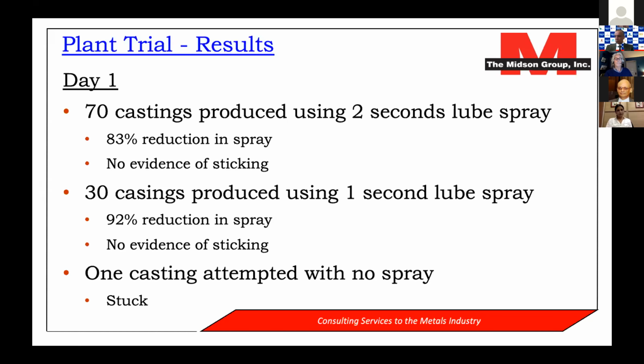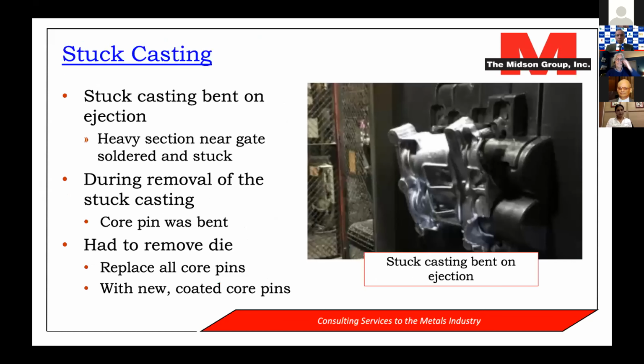And not only did it stick, but it actually bent on ejection, as you can see here from the photograph. And so it looks like heavy sections close to the gate soldered and stuck. And then during removal of the stuck castings, some core pins were bent, so the die had to be taken off the machine and disassembled. Luckily, we had spare coated core pins that we could put back in, reassemble the die, put it back on the machine, and run it the next day.